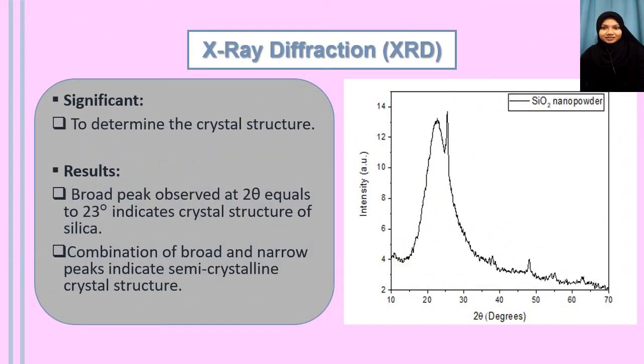Okay, the next result is based on X-ray diffraction. The significance of XRD is to determine the crystal structure of silicon nanoparticle. From the XRD pattern, it can be seen that there is a broad peak observed at 2 theta equal to 23 degree that indicates the crystal structure of silica. The combination of broad and narrow peaks indicates that the silicon nanoparticles are in a semi-crystalline structure.